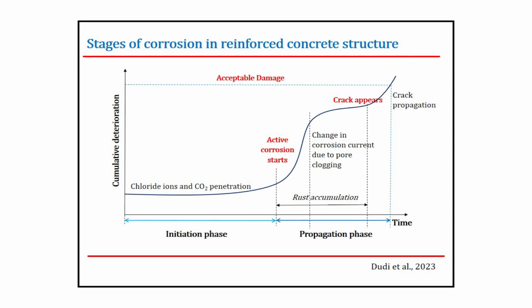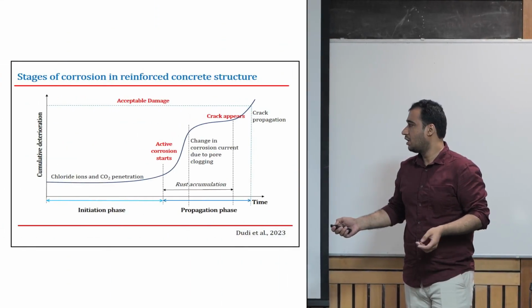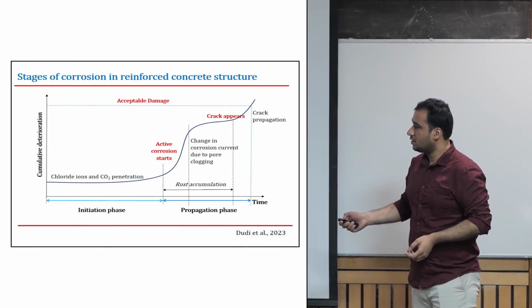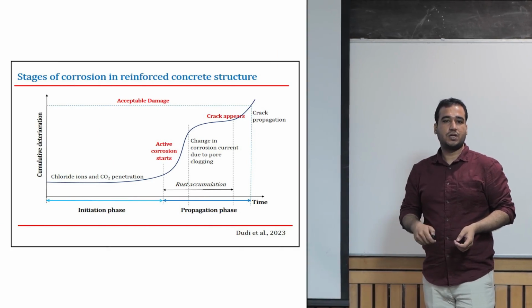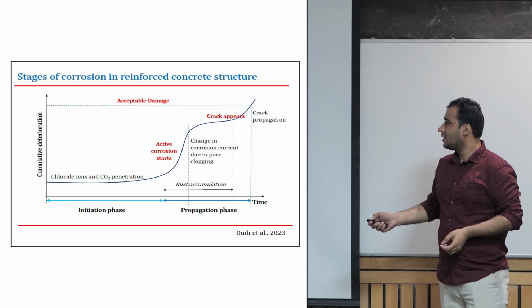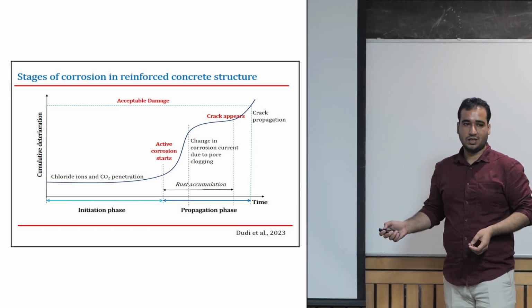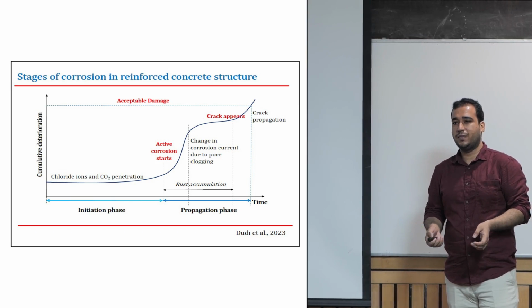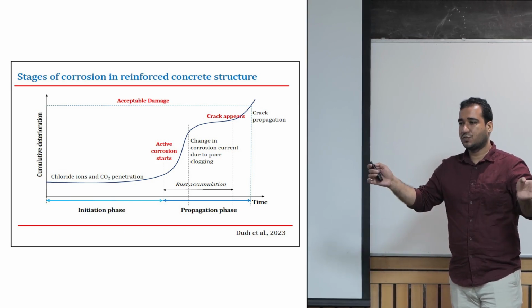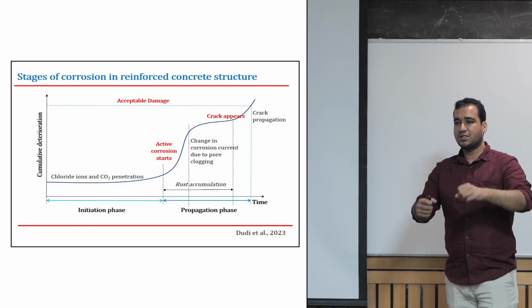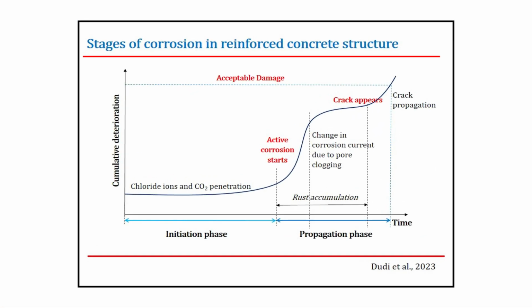Now, the reason for this active corrosion can be different for chlorides than for carbon dioxide. I will talk in detail about that afterwards. So once this active corrosion starts, your rust starts forming. Once this rust starts forming, it keeps building, and the rust has much more volume compared to the parent metal, iron. It can be from 2 to 6 times more than the iron itself. Now you can think, if I have a hole of this size and try to squeeze something more into it, it will start to burst. That's what we say: the cracks start to develop.